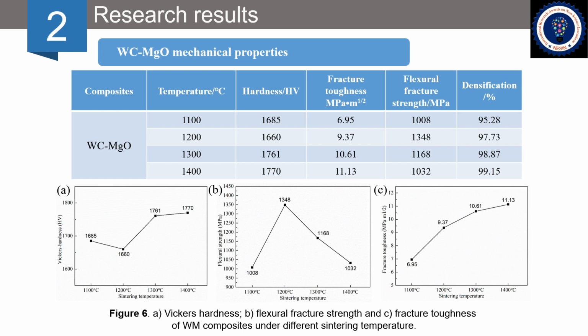From Figure 6a, the Vickers hardness slightly decreased from 1,685 HV to 1,660 HV when the sintering temperature increased from 1,100 degrees to 1,200 degrees. As the sintering temperature rose to 1,400 degrees, the hardness increased dramatically from 1,660 to 1,770. It has shown that the Vickers hardness follows the same law as grain size.